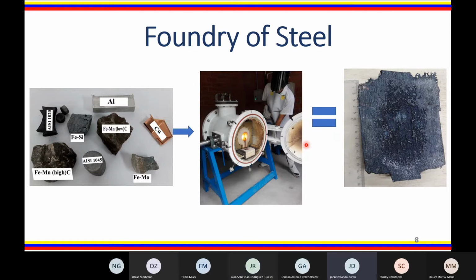To cast these alloys, we start with AISI 1020 and 1045 steel, ferrosilicon, high and low carbon ferromanganese, aluminum, and copper. All these elements are placed in the induction furnace containing alloy plates, like you can see in the figure.